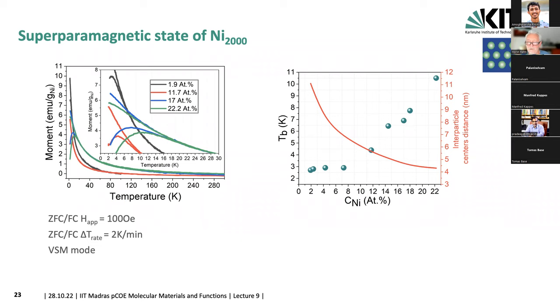And the interparticle distance is plotted here in red. So you see in that range up to 8%, you are somewhere between, let's say, 6-7 nanometer to 10 to 12 nanometer of distance. But once you go above this 10 atomic percent or go below 5 to 6 nanometer in distance, then they start to interact with each other and the blocking temperature goes up. And you see it goes up from 3 Kelvin to almost 11 Kelvin as we approach the 22 atomic percent.